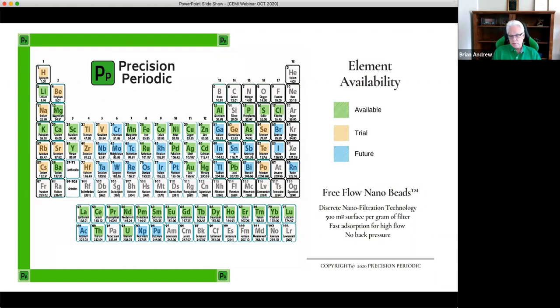Now, one of the things we like to do is stay on the same species. If we leach with a chloride, we get a chloride metal, we want to give that out so there's no translation of species in the filter. So if you're leaching with a sulfuric acid, we'll have sulfates. If you're leaching with a nitric acid, please don't. But if you do, we'll give a nitrate back. And so not changing the species and doing your extraction directly from your liquor based on that species gives you the cleanest mining and, of course, the lowest cost mining. And we also get very good separation capabilities if we understand the species of what we're trying to do. Of course, some elements have several different types of species in a given PLS, but generally we've had good results from that.